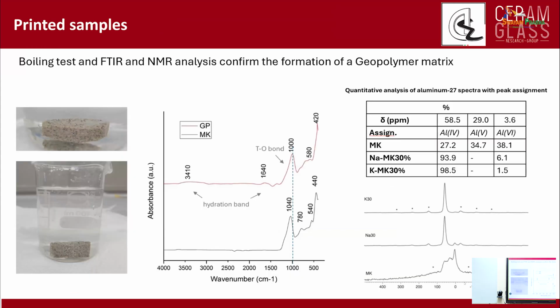So this is a very effective method, and we also tested, not just solid state NMR, but we carried out boiling tests. If you have formed a geopolymer, then you have a 3D continuous network, and therefore the material is non-soluble. If you have an incomplete geopolymerization and you carry out a boiling test, the material will at least partially dissolve. And another way for checking that geopolymerization has occurred is by FTIR. The silicon oxygen band for metakaolin is about 1040, and if it is around 1,000 or below, then this is a confirmation of the generation of silicon oxygen aluminum bonds in the material.